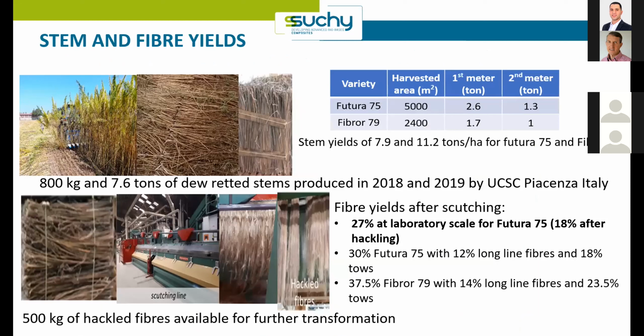to our results, you can see that some hemp was harvested. And what is important is to look at the stem yield, because growing hemp is possible in many places in Europe. It's been proved for many years, but to what extent the one which was grown in the frame of SUCHY is suitable for industrial production. And you can see in those results that depending on the variety, between 8 tons and 11 tons per hectare of stems and of retted stems were harvested. It's a lot. It's a very high yield, and the work which was done was obviously very good.